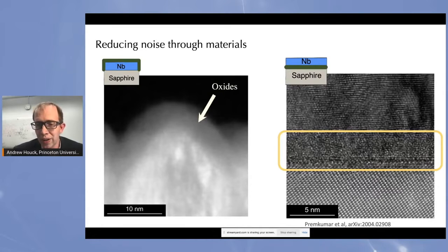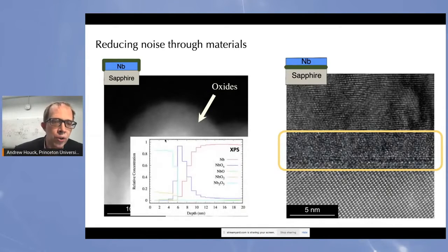It doesn't quite look like a crystal. At the bottom, you can see the individual atoms in the sapphire. They look beautiful. Things are relatively ordered up top, which is good, but this mess here at the interfaces is not very good. If you look more closely at the oxide, you can actually measure how thick it is. So going from left to right, you're going from top to bottom. This light blue color is the oxide. That being thick is very bad for the coherence of the system. But even worse is this big purple peak in the middle. This is oxide that is not stoichiometric. It's sort of a very messy and ill-defined kind of thing, which tends to be extraordinarily lossy.